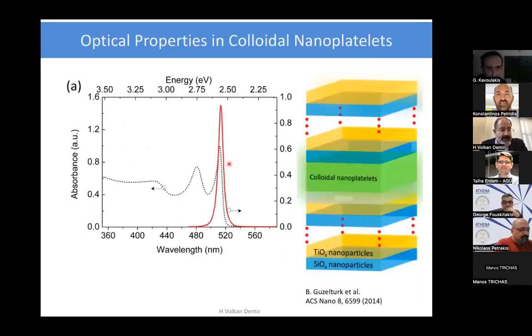This is one, I'd say, textbook example that I like showing, where you can see room temperature photoluminescence from these colloidal quantum wells. Quite sharp in emission. Here, full width half maximum is about 8 nanometers. And on the background in black dotted curve, you can see the absorption profile. These are heavy hole, light hole absorption peaks, excitonic peaks, and a plateau absorption profile. This is pretty much a textbook 2D quantum structure one would expect. And this is, for us, an ideal platform to explore further.